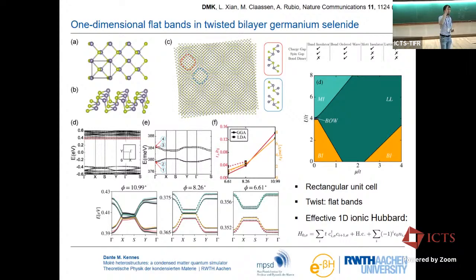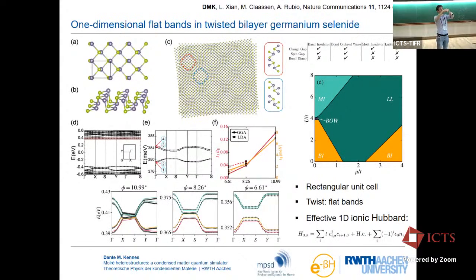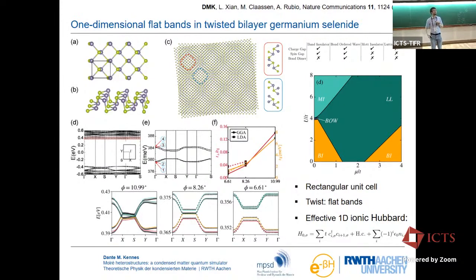No, I'm taking a monolayer, and then twisting. And this is the dispersion in the 2D plane. So we don't have a Z direction. Okay, so we take these two-dimensional systems, we put them on top of each other, we twist. We get dispersion only in one direction in this two-dimensional plane, and not in the other. So you can really take two-dimensional systems and effectively engineer one-dimensional physics.